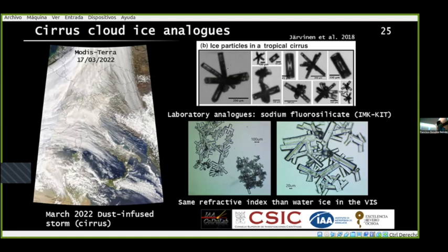These ice particles have been measured by aircraft collection measurements. And we are interested in knowing the radiative forcing introduced by such an event. But the problem is that it's very difficult to work with water ice in the lab. So as an alternative, what we can do is use laboratory analogs. Sodium fluorosilicate is an analog that crystallizes similarly. It forms these nice columns which agglomerate forming rosettes. Our colleagues at IMK, KIT are producing these analogs. We have them already in the lab, and by suspending them in the levitator, we will be able to determine the scattering properties.